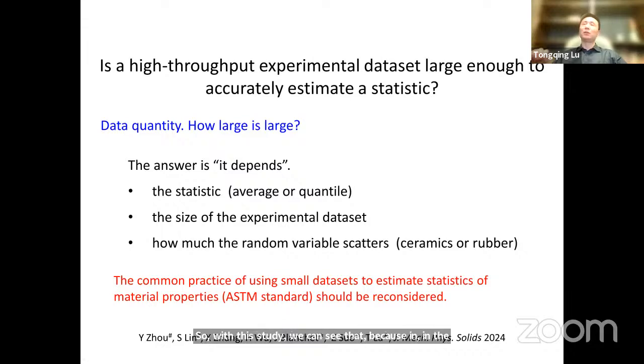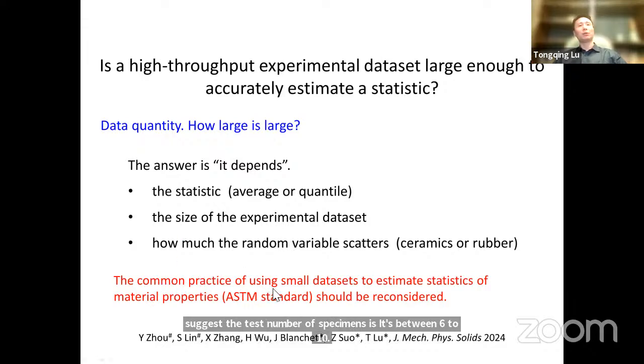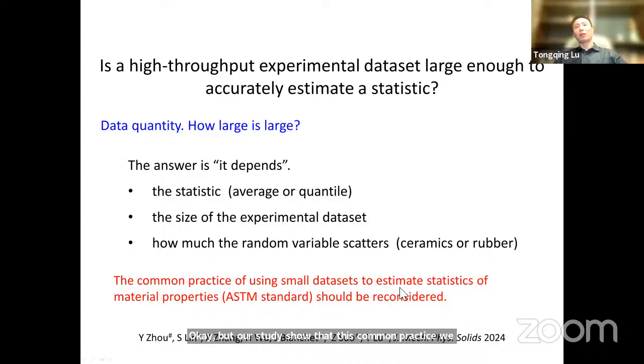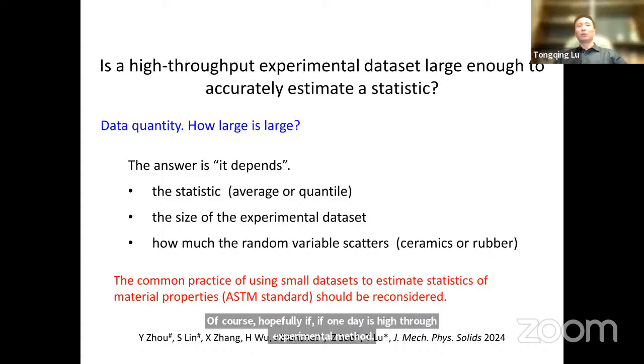With this study, we can see that in the standard, for example the ASTM standard, for strength tests they usually suggest the number of specimens be between 6 and 10. But our study showed that this common practice of using small data sets to estimate statistics should be reconsidered. Of course, hopefully, if one day this high throughput experimental method can be widely adopted, the standard should be changed.